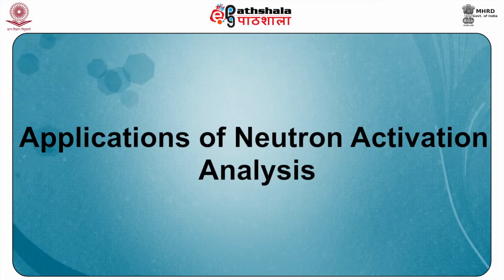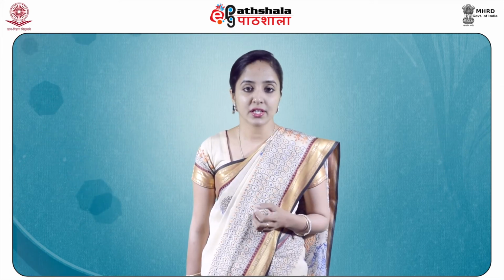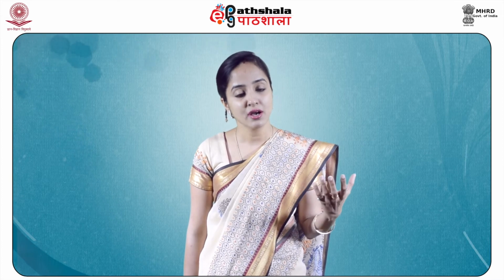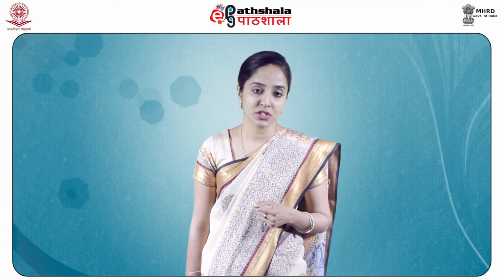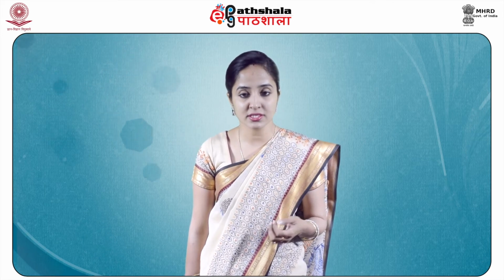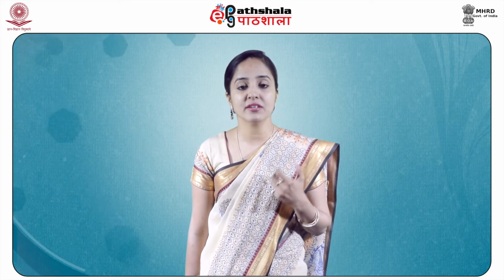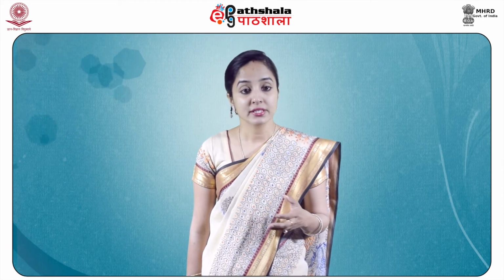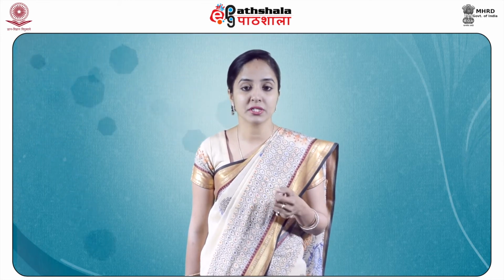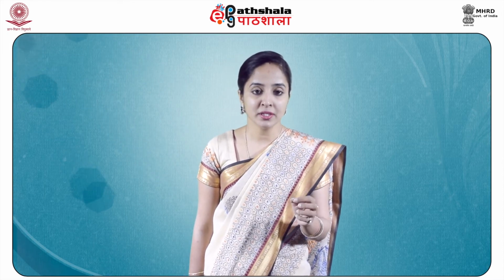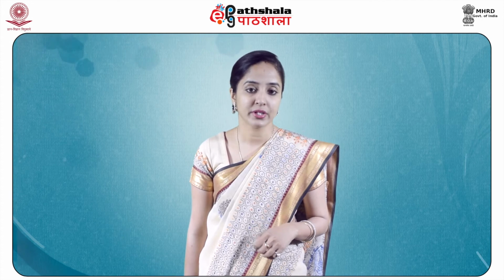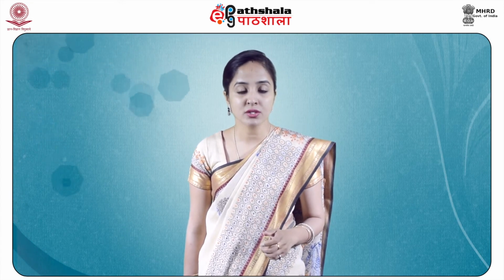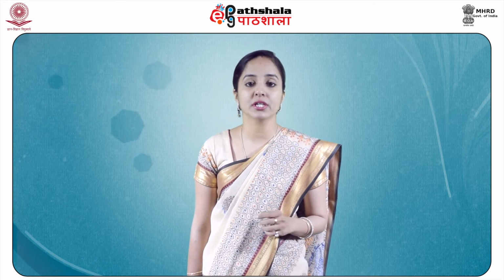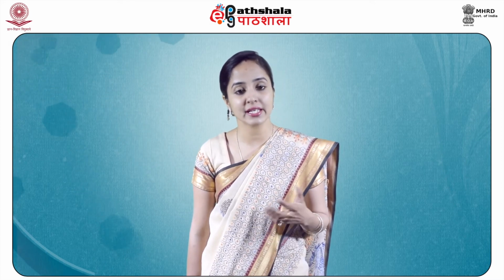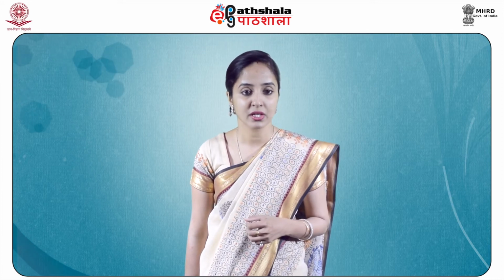Now we talk about the application of neutron activation analysis, students. What are the applications in industry as well as in forensic science of neutron activation analysis? Neutron activation analysis measures the total amount of an element even in extremely low concentration, that is even in parts per trillion or lower, in a material without regard to chemical or physical form. Samples analyzed can be liquids or solids and do not have to be put in solution form as in other techniques like AAS and ICP as discussed earlier.